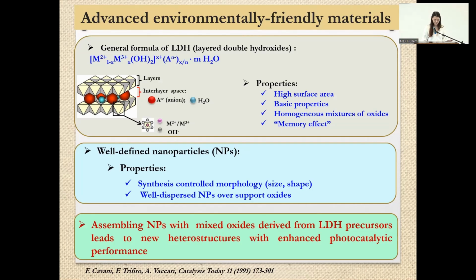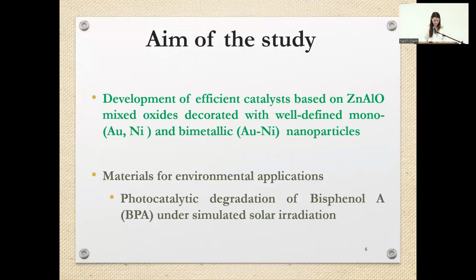For example, for the LDH, short for layered double hydroxide, we have high surface area, basic properties, a homogeneous mixture of oxides, as well as the memory effect specific to the LDH. The well-defined nanoparticles present properties such as synthesis-controlled morphology and well-dispersed nanoparticles over support oxides. Assembling nanoparticles with mixed oxide derived from LDH precursors leads to new heterostructures with enhanced photocatalytic performance.